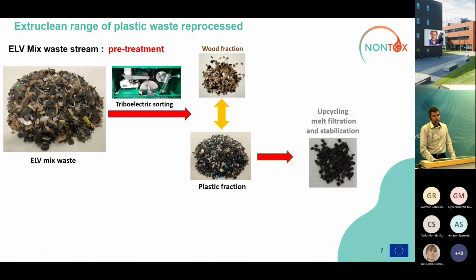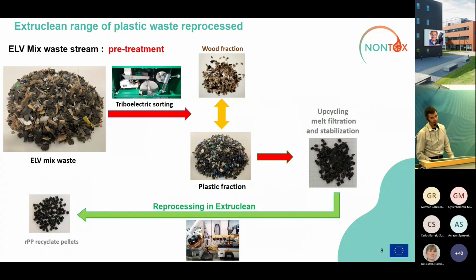We performed an additional stage consisting of melt filtration and stabilization of this plastic fraction prior to reprocessing in the Extruclean process. So also at the end, we were able to obtain polypropylene recyclates with lower VOC content.